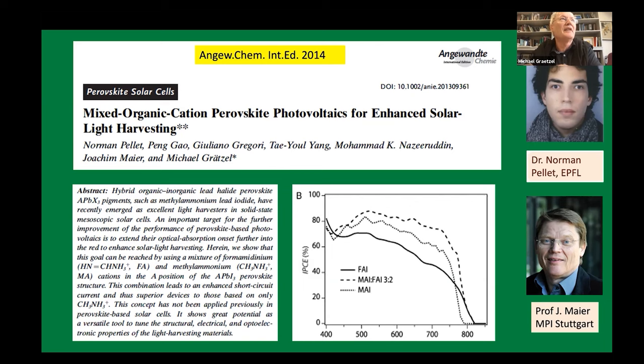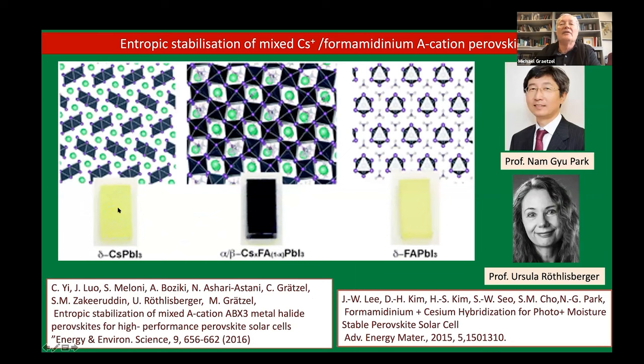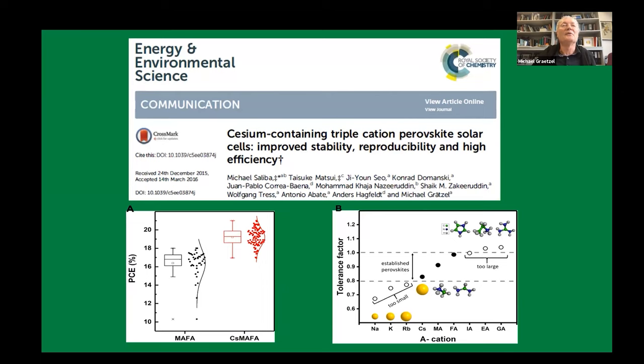The reason for the stabilization is mainly an entropic effect. If you want to form a mixture with the delta phase, that's energetically more expensive — you have an energetic barrier, but you also have entropy helping you. That's even more so the case for a mixture of formamidinium and cesium: both are yellow phase at room temperature, but you grind them and lo and behold you get a black film. It's thermodynamics — but we have to realize the entropic contributions depend on temperature via T times delta-S, so at lower temperatures you can reach limiting stability.